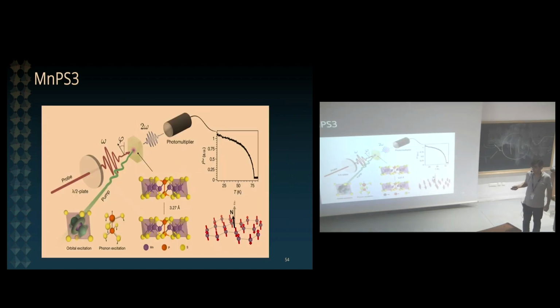Right. So manganese thiophosphate is a kind of useful material for magneto-optics because it's a system that undergoes a transition to an antiferromagnetic state at around 75 Kelvin. And in this low temperature antiferromagnetic state, the spins cause a breaking of inversion symmetry, which results in a very large second harmonic generation occurring in the low temperature phase. So we have this nice optical probe of this antiferromagnetic transition. So we send a probe pulse oscillating at frequency omega, and we measure the frequency 2 omega. And we can do this when we excite with the pump either phonon excitations or orbital excitations. All right.